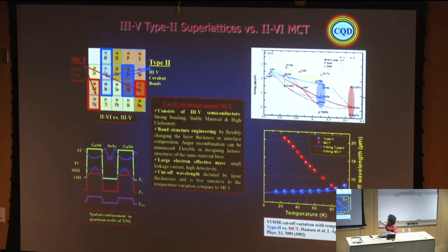Come here. If you put indium arsenide and gallium antimonide side by side, in very thin layers, the conduction band of indium arsenide is at lower energy than the valence band of gallium antimonide. So when you put the thin layers together in the direct lattice, you have separation of electron and hole. The hole goes to the gallium antimonide and the electron to the indium arsenide. But if you look in the reciprocal lattice, the minima of the conduction band and the maxima of the valence band are just at the center of the Brillouin zone.